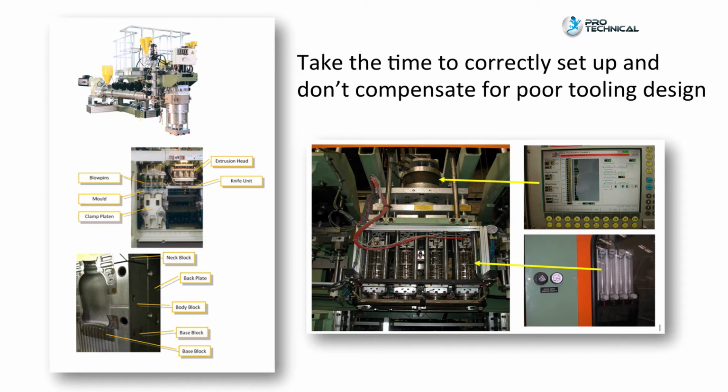Contaminants building up on the extrusion die. Well, you'll see the parison swing and vary in small amounts. Many technicians will adjust the support air to compensate rather than cleaning the extrusion die. It's much easier to do than stopping the machine. But once the extrusion die is cleaned, then the support air will be incorrect and then it'll have to be set again. Locking away controls and only allowing technicians to do basic cleaning during production runs will actually save you a ton of trouble over a long period of time.